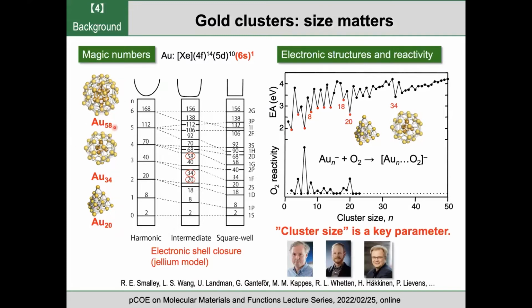20, 34, 58. And the high stability of these magic clusters has been explained by the closure of the electronic shell. So the 6s electrons in gold atoms are accommodated into discrete orbitals created within the jellium-like potential of the clusters. So when the total number of electrons satisfies these numbers, 2, 8, 18, 20, and so on, the clusters become stabilized because of the closure of the electronic shell.